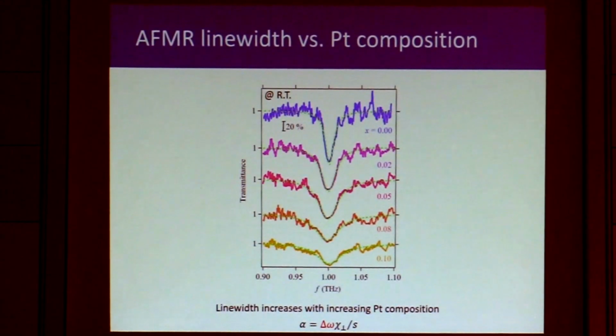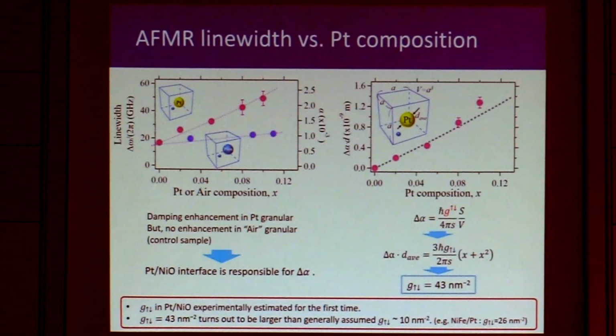So the most important part is the characterization of the linewidth. We take the linewidth here. This peak is right at 1 terahertz. And as we increase the platinum composition, the linewidth just gets broadened. From this data, we plot the linewidth, or the damping, as a function of platinum composition. For the control sample, we also created an air granular sample where we have air pores instead of platinum particles inside the nickel oxide. As you can see, there's a slight increase, but the linewidth difference is distinct. So from this data, we can say that the platinum nickel oxide interface is responsible for the enhancement of damping.